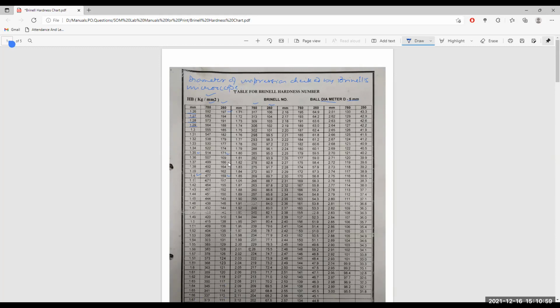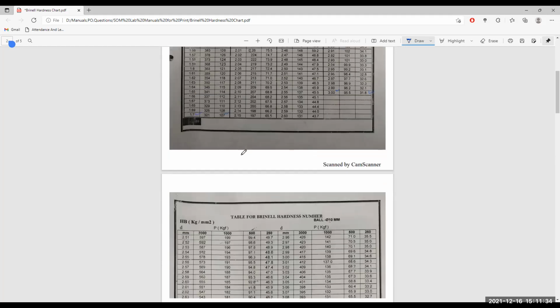Lower hardness can be checked, say for 250 kg load here, 250 kg indenter with a 5 millimeter ball. Hardness can be as low as 31.8, where the diameter of the impression of the ball is equal to 3 millimeter. Means with a 3 millimeter diameter ball, the impression is achieved around it. So the hardness will be as low as 31.8 kg per millimeter square, or simply 31.8.